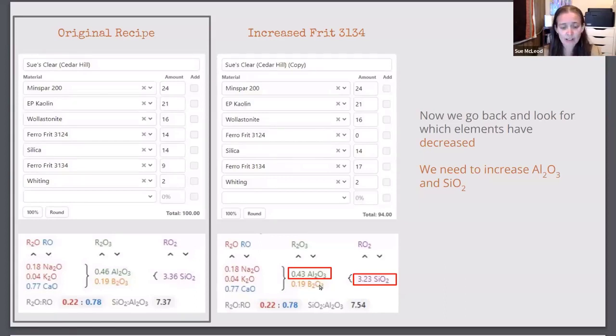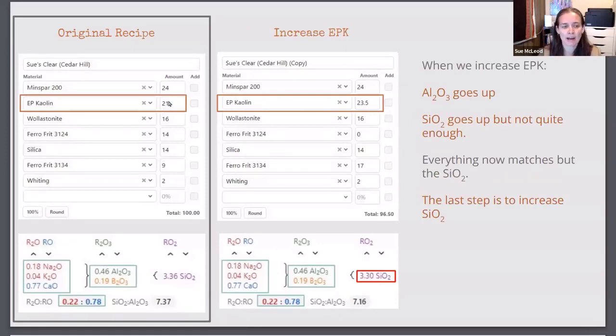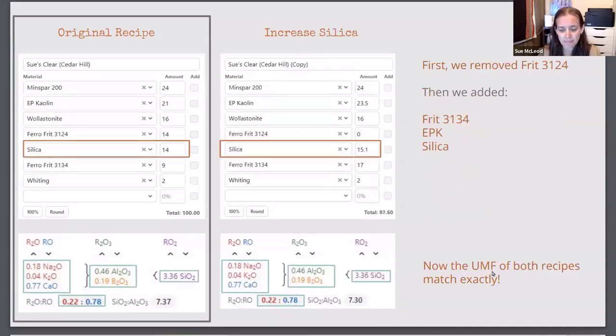So in order to increase the alumina level to 0.46 to get these numbers to match, I'm going to increase my clay content. So I went up just a couple percent, and now the alumina level matches, the boron still matches, the fluxes still match. So now I'm left with the silica. I just need a little tiny bit of silica to bring this number up to match this one. And so I can just increase the silica by 1.1%. And now the whole UMF matches.